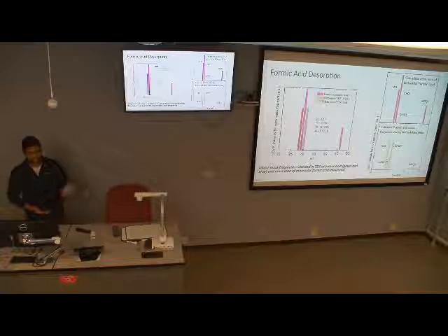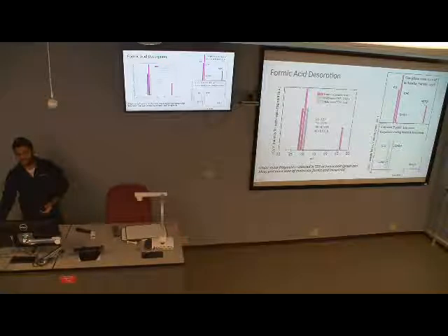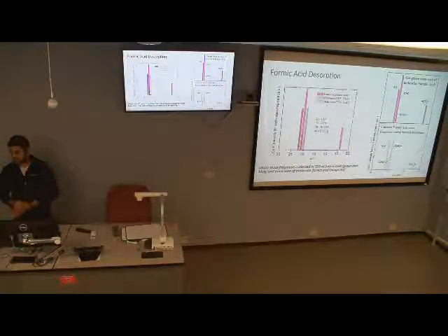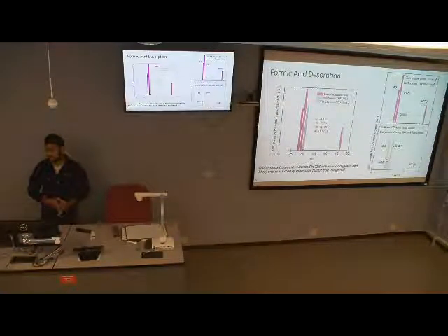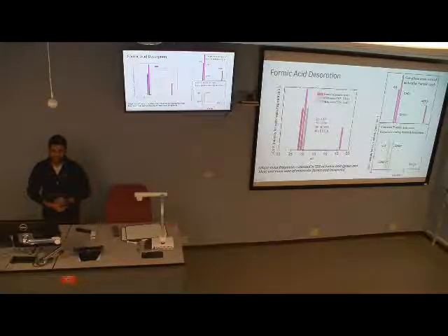So the same thing is formulated in a different way here. We have the gas phase mass scan here, and then the collected formic acid mass fragments. This time those fragmentation peaks were integrated and the intensities were normalized and put in here. If we have molecular desorption, we should see similar intensity ratios of these peaks in both cases, but the gas phase mass scan and the collected formic acid fragmentation pattern have two different intensity ratios. That confirms the dissociative adsorption of the formic acid molecule.